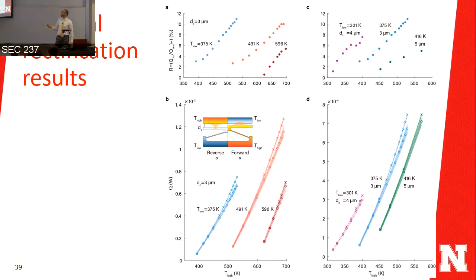You see that the initial separation gap between the moving and fixed terminals, and we measure this at several temperatures. For the lower temperature, you can see here that always the forward bias has higher heat transfer than the reverse bias. And we can achieve the rectification at temperature as high as 600 Kelvin. And these results are for different separation gaps of 3, 4, and 5 microns.